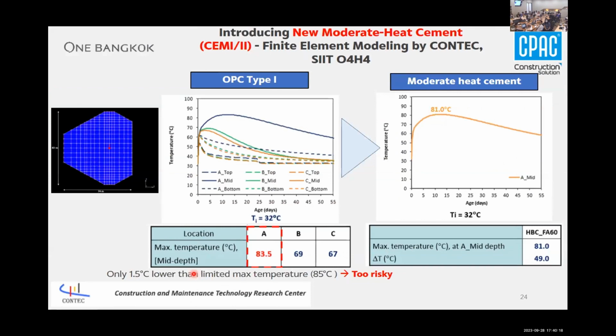And as I mentioned, in Thailand, we use OPC cement in general. So for this project, we would like to use OPC as well. Before we cast, we try to simulate the model, and this one is what the shape of the foundation looks like, and we get the peak temperature around 83.5 degrees Celsius. At that time, we talked to the owner and the consultant, but the owner and consultant said that it's too risky. We have only 1.5 degrees Celsius to spare. So this number is quite high from the model from Professor Somnik and SIIT.